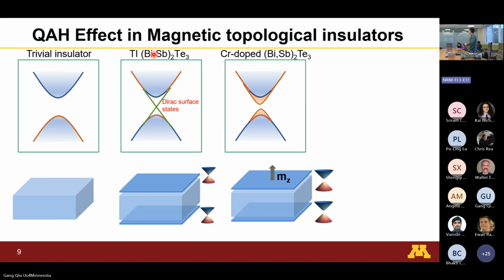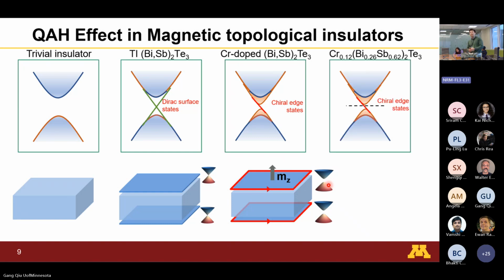Now you have an insulating bulk and an insulating surface. Basically, this thing is almost entirely insulating, except if you look at the edge of these surface states, you have a circulating current. We call them chiral edge states because you only have one spin going in one direction, because now you only have this one branch. And if you look at the group velocity of these edge states, it's all just one number. That's why you only have a singular circulating current state on the edge. The one last thing is you fine-tune the material composition a little bit so that you move the Fermi level right inside this gap. So the bulk really becomes insulating, the surface is insulating, and you only have chiral edge states.